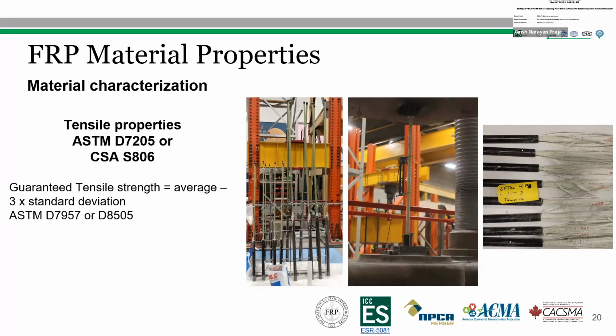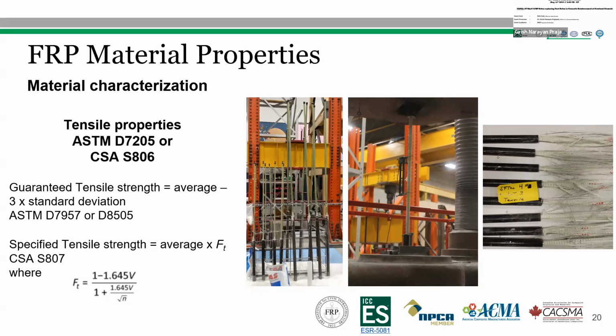According to ASTM D7957 or D8505, the guaranteed tensile strength was calculated by subtracting 3 times the standard deviation from the average tensile strength from the test. While CSA S807 recommends using a specified tensile strength found by multiplying the average value by a factor F_T. This factor is calculated by the following equation, where V is the coefficient of variation and N is the total number of samples.